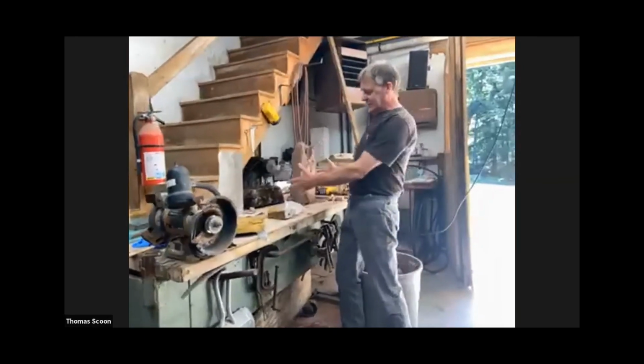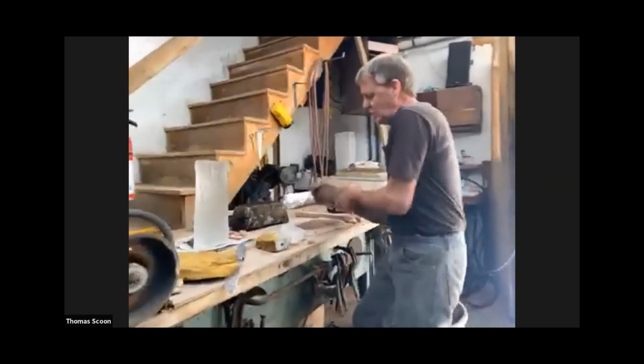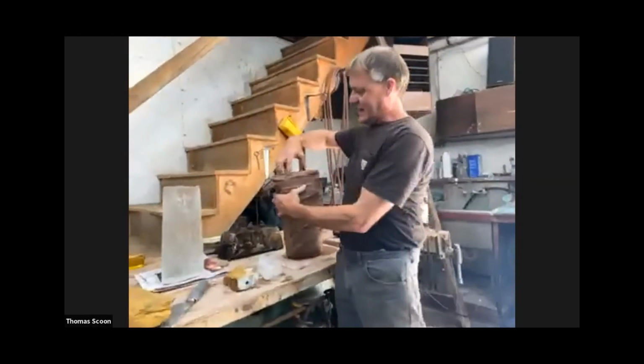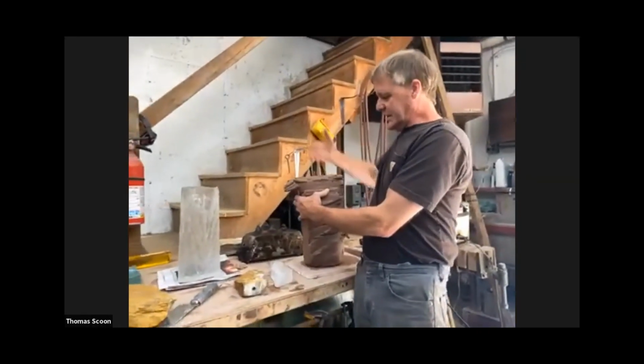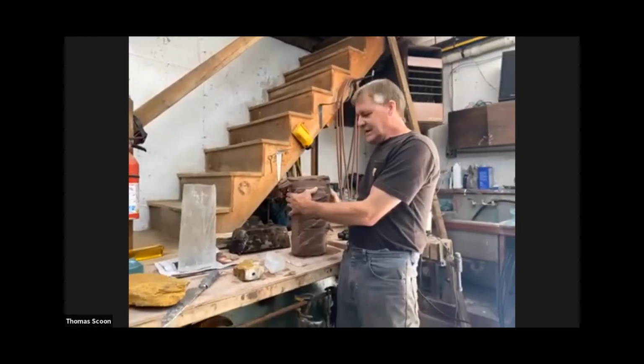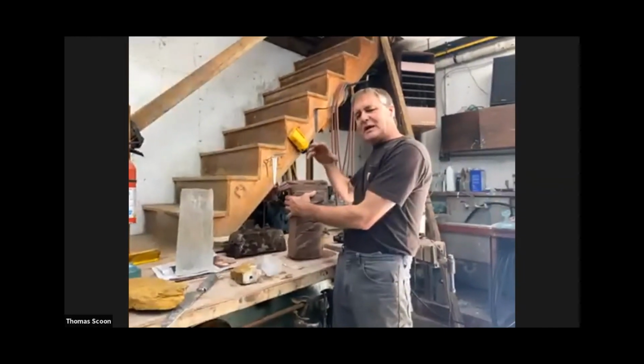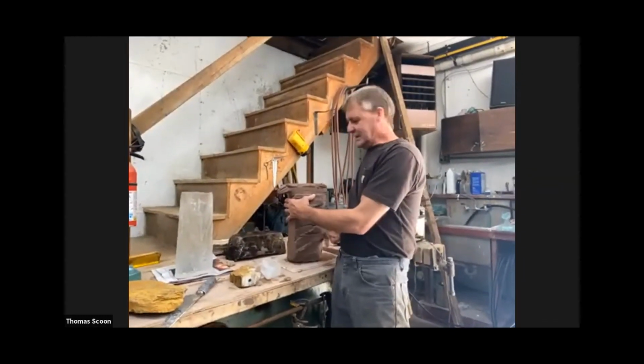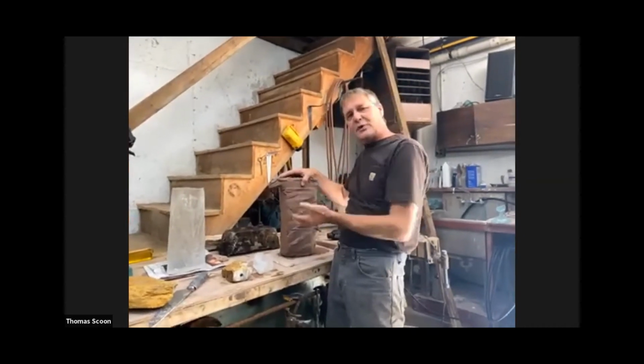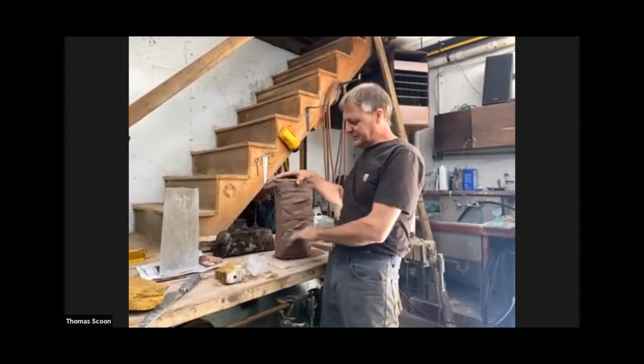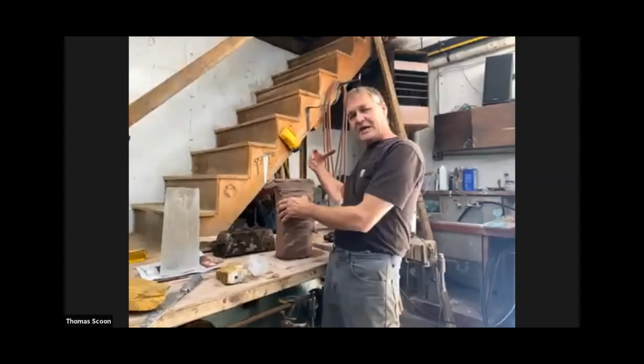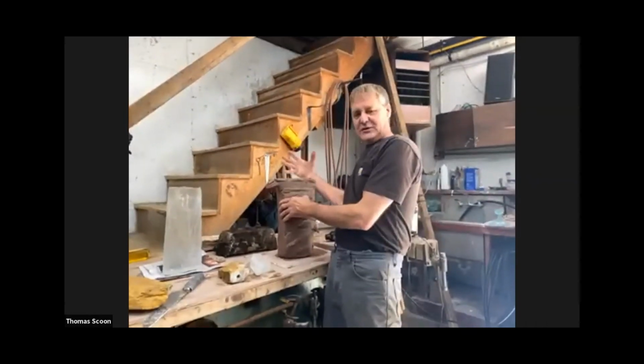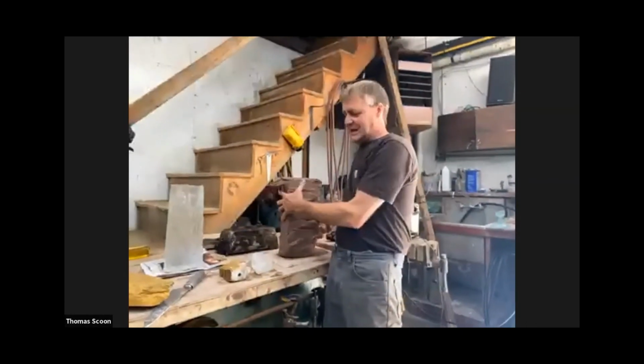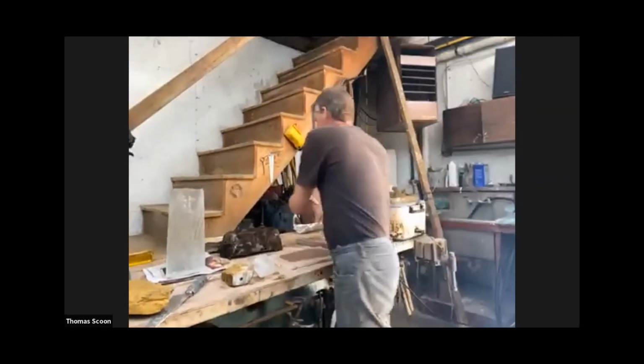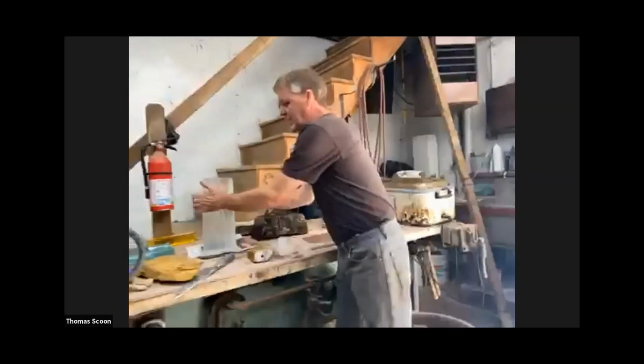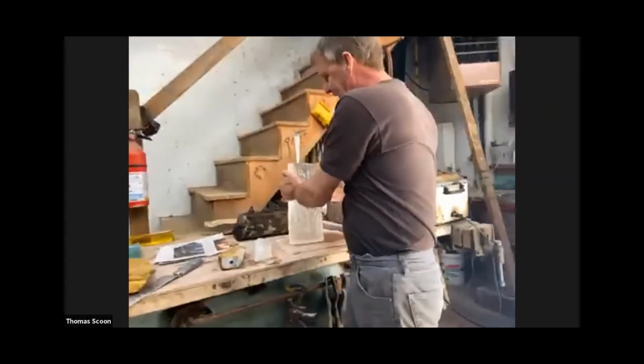So basically we have a chunk of plaster, we flip the mold over, and all you see then at the top is this clay area. Take a knife, dig the clay out, and you have the negative of that shape in a mold. It goes in the kiln. You put cold glass in here, you bring it up to 1650, that glass melts, you add it, and then it fills, and you have that form cast in glass, and then it slowly has to anneal. So break the mold apart if everything is okay.